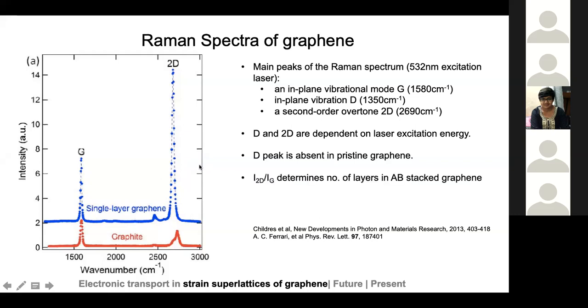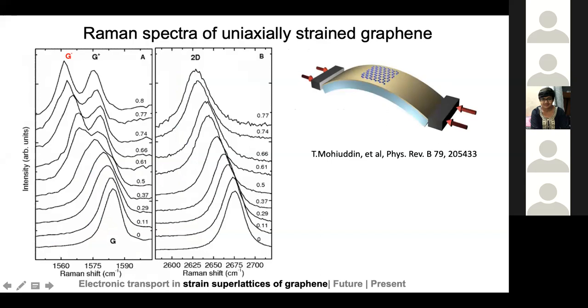And so the ratio of the intensities of the 2D peak to the G peak gives you an estimate of how many layers of graphene there are in your system. So the lesser the number of layers, the higher will be this ratio. And the ratio of the D peak to the G peak gives you an idea of the disorder which is generated in the system. If you don't have much disorder, your D peak is expected to be lower. So with that in mind, let's look at how the Raman spectra varies with strain.